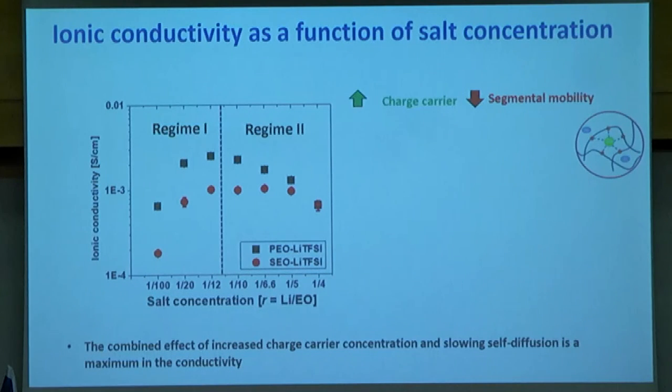In polymers, we have additional phenomena, the main effect being a cross-linking effect, because the polymers, especially PEO, bind strongly to the lithium. As you add more and more salt, even from the beginning, you change the dynamics, you slow the dynamics. And we talked about how dynamics are important, right? Because you really need the polymer to move a little bit for the ions to reorganize and move. So when you put in those lithiums, they coordinate so strongly that you can have a kind of cross-linking network that now slows down the movement. So what we can see is that with the homopolymers people observed before, there is a peak, a maximum, and the conductivity really goes down.